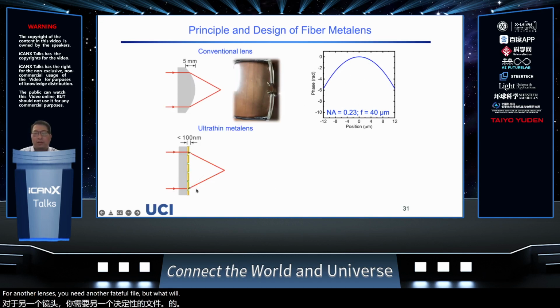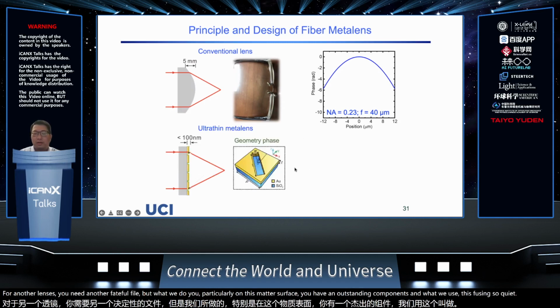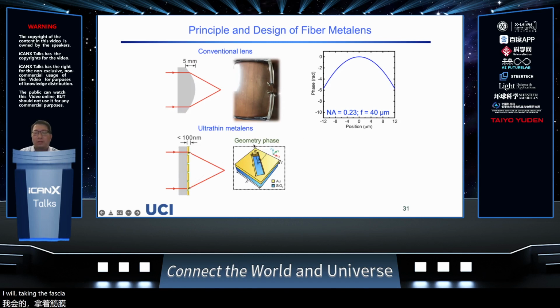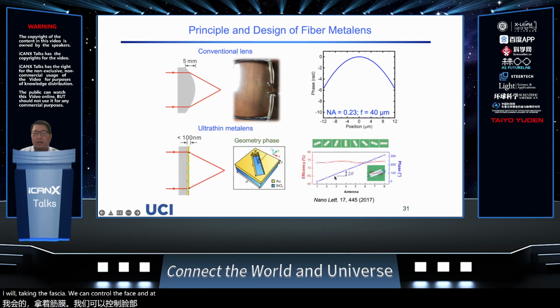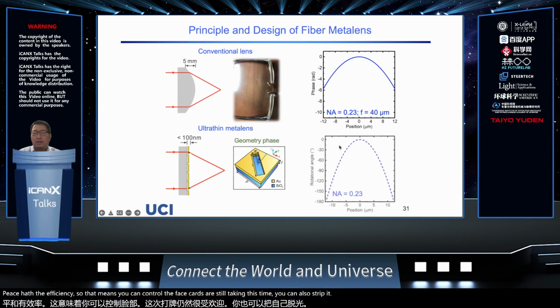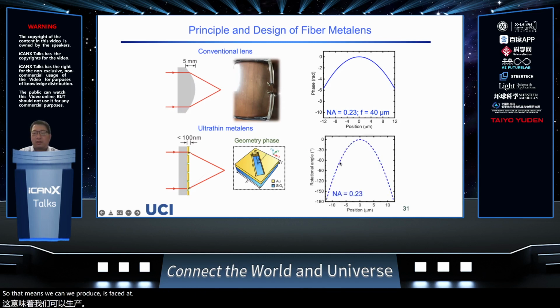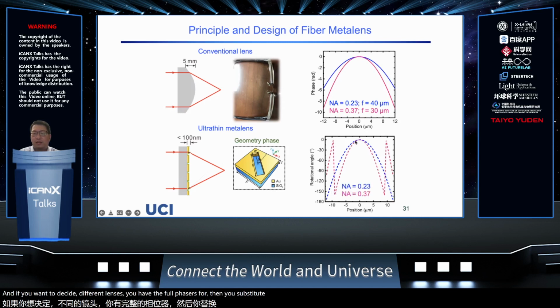But what we do basically on this kind of metasurface, you have an ultrathin component, and what we use is the so-called geometric phase here. By rotating the structure, we can control the phase, and at the same time, you can preserve the efficiency. So that means you can control the phase by just rotating this tiny nanostructure. We produce this phase distribution by just rotating the structure of this metasurface unit cell, so then you can obtain the phase you need. And if you want to design different lenses with different phase responses, then you just need a different rotational distribution for the other lenses.